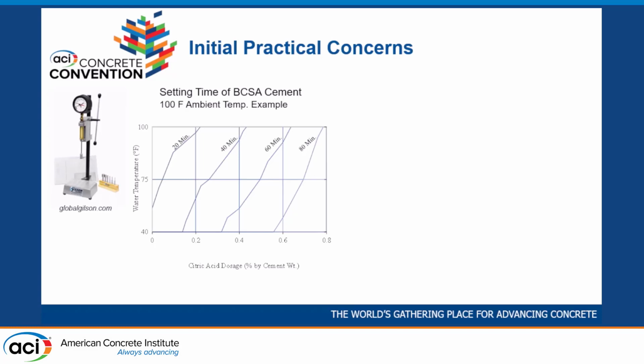So we've done a bunch of setting time tests. This shows at 100 degree Fahrenheit ambient temperature, different water temperatures, 100 degrees, 75 degrees, 40 degrees Fahrenheit, and a bunch of different water cement ratios, what setting time you can expect. So if it's 100 degrees outside and it's 75 degree water temperature, we would use about 0.5% citric acid by cement weight to get about 60 minutes of setting time. Most of the time in our lab, at normal lab temperatures, we use something like 0.35% citric acid, which gives us around 45 minutes of working time. So we try to work really quickly.